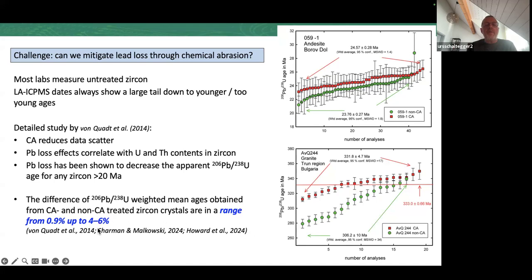There is quite a bit of statistical modeling done, which is nice, but in a way, a statistical treatment of bad data is not what brings us away from this difficult situation. What we should do is try to improve the boundary conditions, and doing thermal annealing of all grains we analyze afterwards for laser ablation uranium-lead dating is a minimum effort and would probably remove some of this scatter. But I'm not aware of any really significant study.